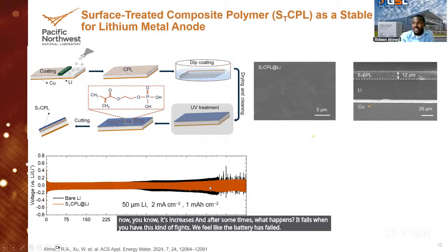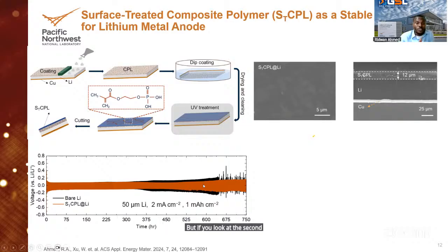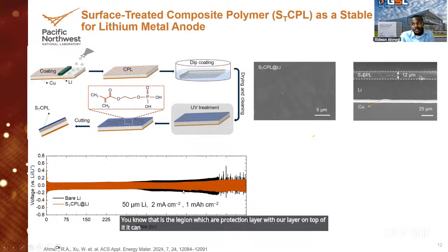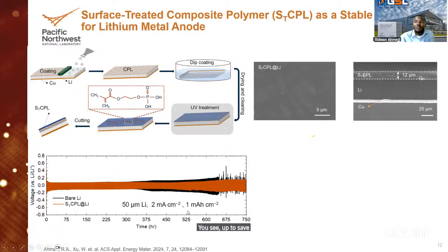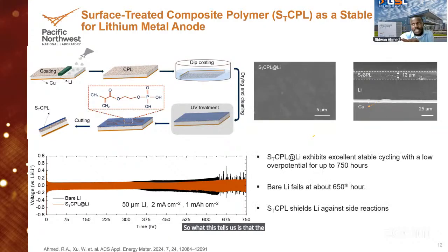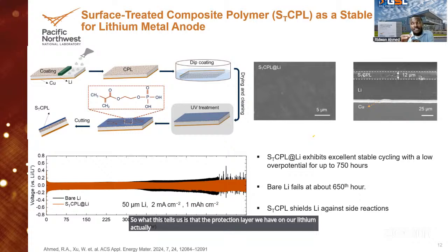But if you look at the second one here, which corresponds to the protected lithium, that is the lithium with our protection layer on top of it, it can withstand a longer cycle. You see, up to 750 hours compared to the bare lithium. So what this tells us is that the protection layer we have on our lithium actually shields the lithium against side reactions with the electrolyte.